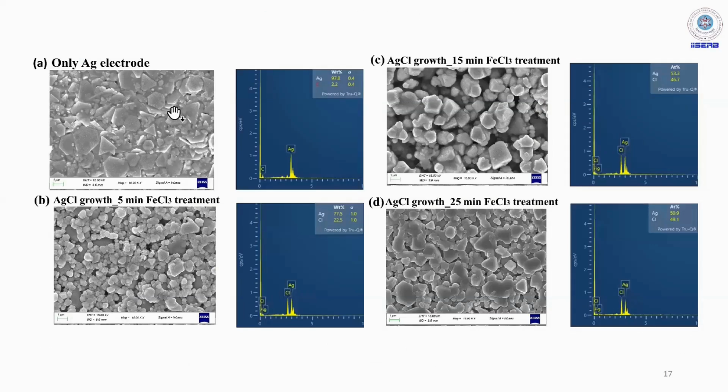This is again the FESEM image of the gate electrode, where we could see the formation of AgCl with time. So we treated this particular gate electrode for 5 minutes, 15 minutes, 25 minutes, and then we could see after 25 minutes, it more or less has formed Ag/AgCl.